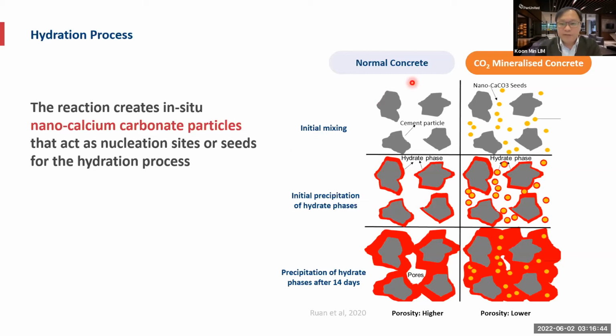Okay, over here on the left-hand side, under normal concrete, you can see this gray color. These are the cement particles. And during the initial precipitation, when water is added, the red color represents the hydration products being formed around the cement particles. And this continues to grow after 14 days. As you can see, more hydration products are formed around the cement particles. And typically, these hydration products are the ones that give strength to the concrete.